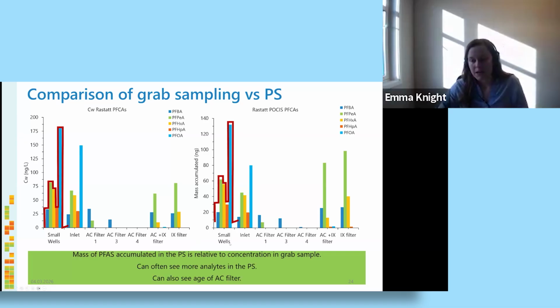Secondly, we can also see more in the passive sampler extracts than we do in the grab water sampling. And this is because we get a lower limit of detection of our analytes in the passive sampler, because they've been there for longer, they absorbed more of this average concentration over time. And so when we look at this, and yes, the bars are very small, but in activated carbon filter 4, we see a little bit of PFBA. In the pilot treatment steps for the activated carbon plus the ion exchange filter, we see a little bit of PFHpA, where we don't see that in the concentration from the grab sample. And as expected, with an increase in treatment step, we see a decrease in our concentration measured. So that's great, because we don't want to be sending out contaminated water to the public.